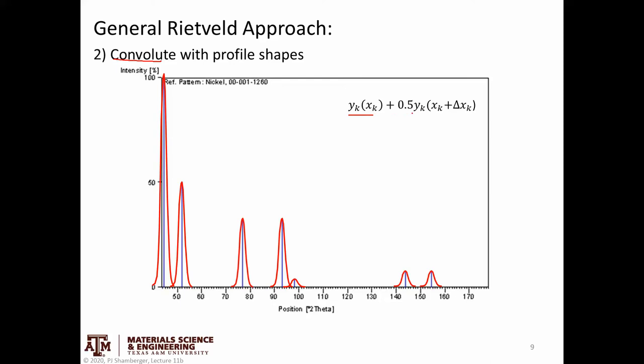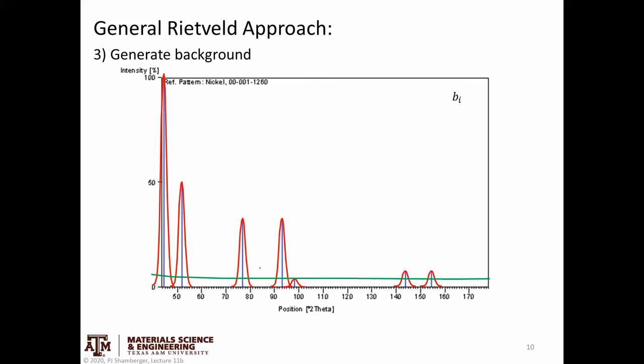One example of profile shape considerations: in a real diffraction system we often have multiple wavelengths. In a lab system we use copper K-alpha, but there's actually a K-alpha-1 and a K-alpha-2 fluorescence line, meaning two very closely spaced wavelengths of radiation interacting with our material — all of which gets taken into account in the profile shapes. There is also a general background, fit with a linear or polynomial function, representing background scattered radiation that occurs at any angle when your sample is hit with X-rays.